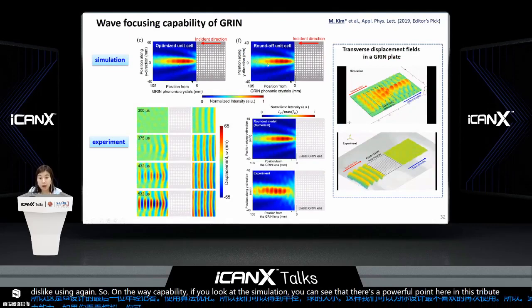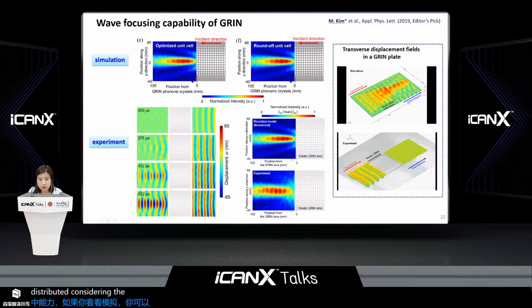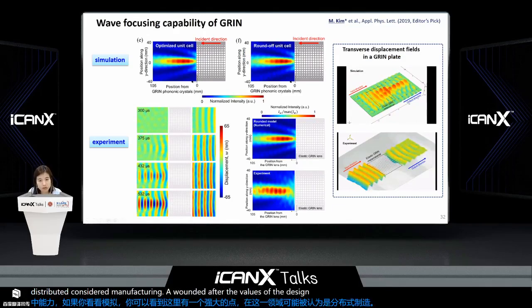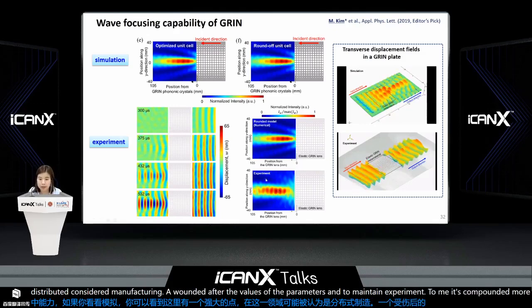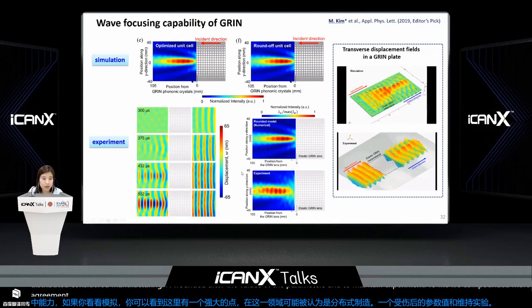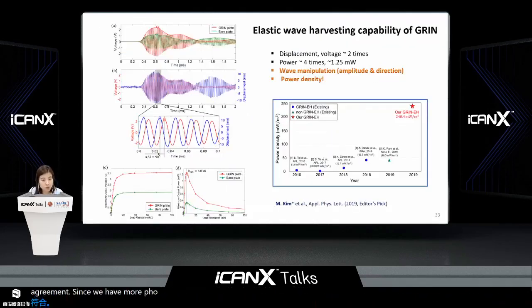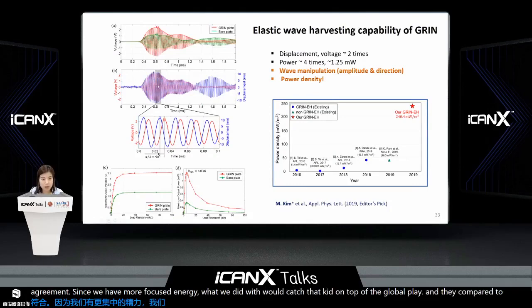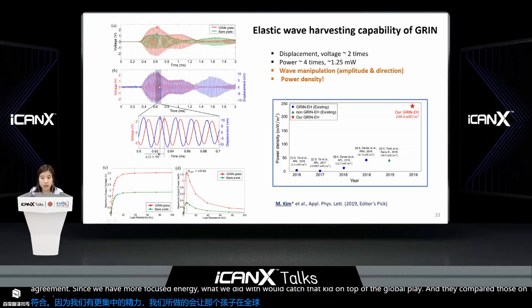And considering the manufacturing tolerance, we rounded off the values of each design parameter, and we looked at the performance; the focusing capability is still maintained. Experimentally, it's confirmed as well, and they are in great agreement. And since we now have focused energy at the focal point, we attached the piezoelectric device on top of the focal point, and we compared the energy harvesting capability with and without GRIN structures.